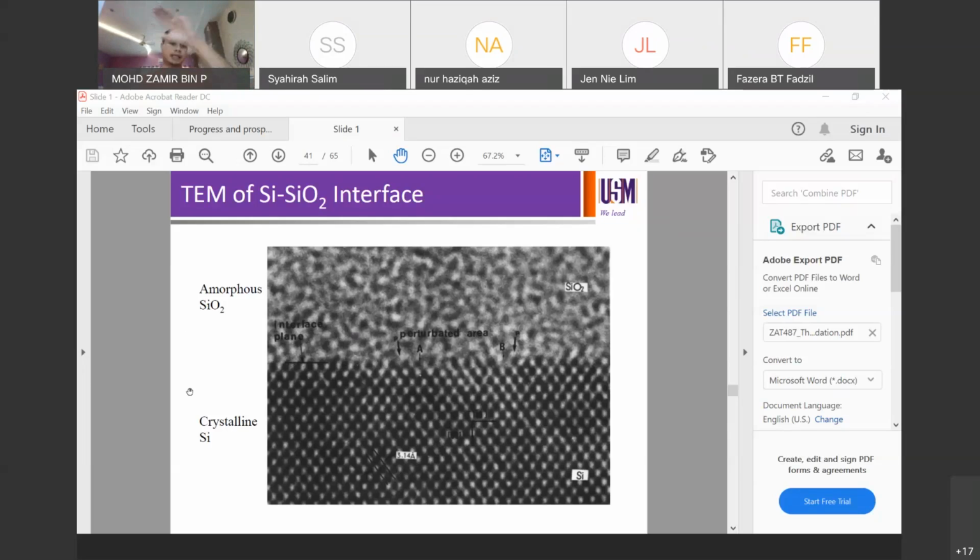SEM, you will see layer A on layer B, but you can't see the lattice arrangement or any particular lattice arrangement, right? That can only be obtained by TEM characterization. So that's why TEM, if you send one sample, it can be up to 400 plus, 500, 600 per small sample. If you send an FIB sample, it will probably cost you 500-600 per characterization. On the other hand, SEM will probably cost you 150-200 per characterization, right? Due to the strength of the TEM.